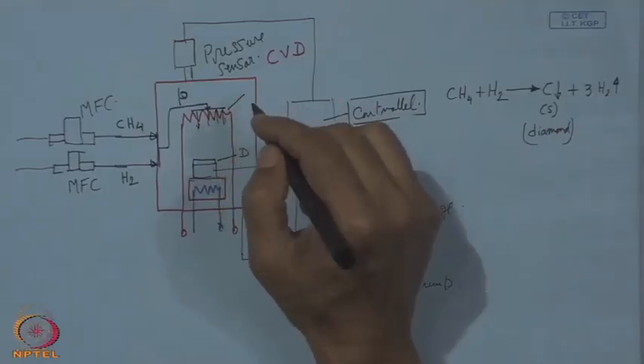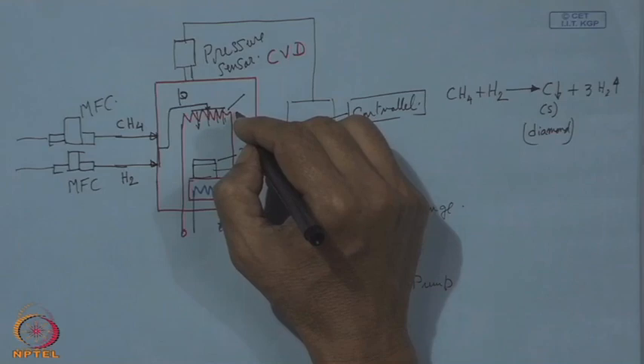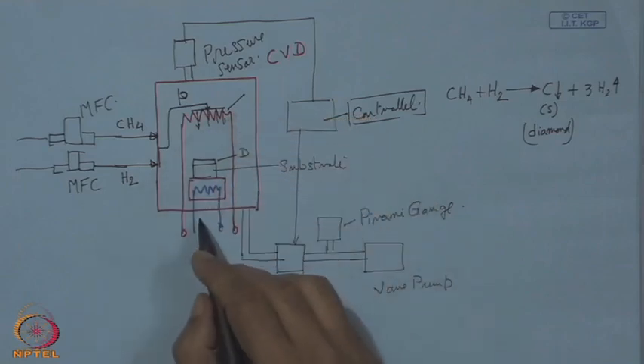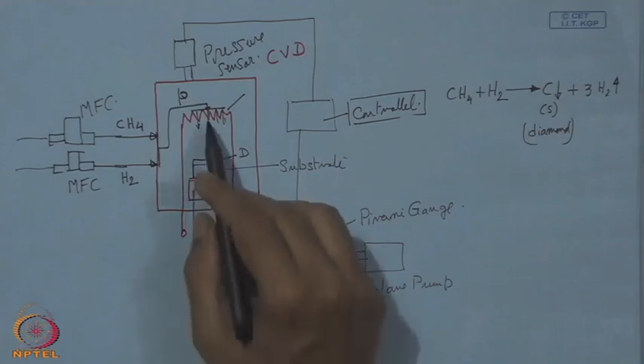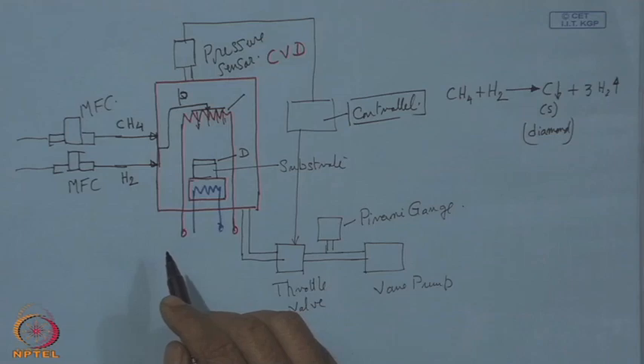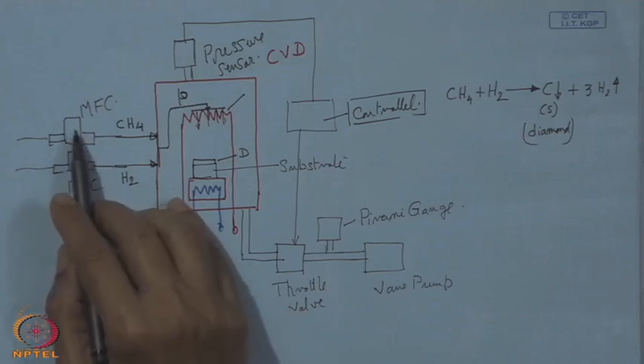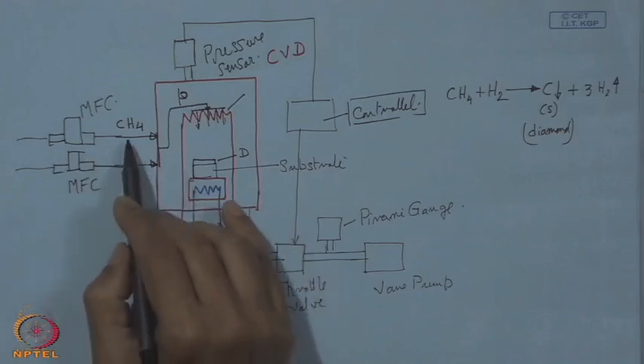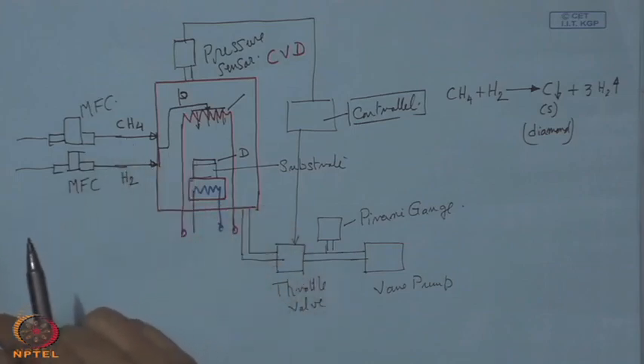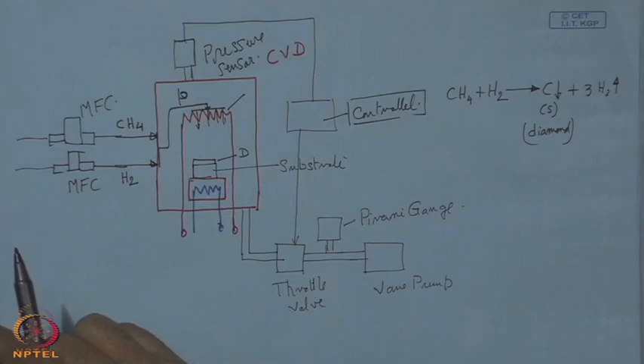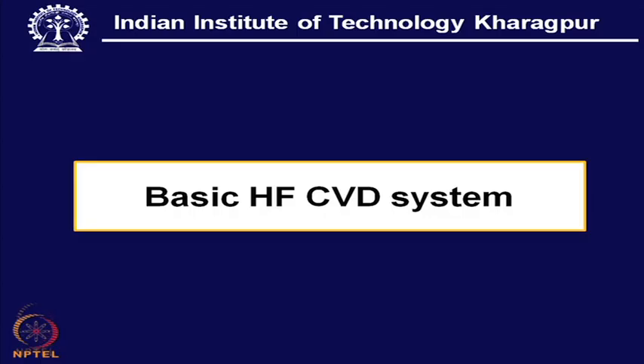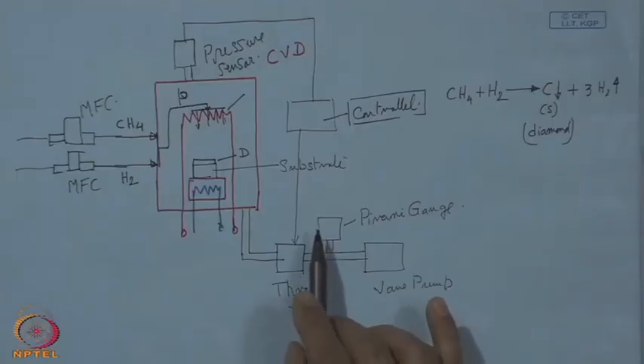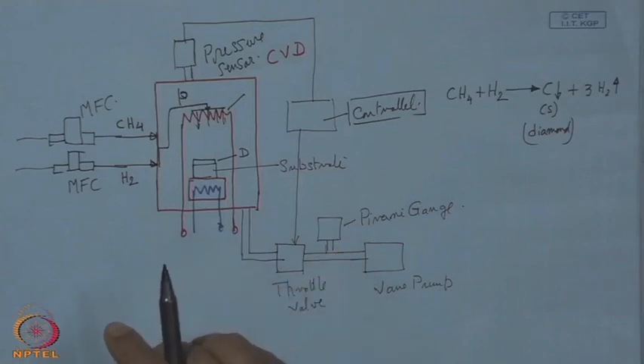Now, here the filament temperature is to be monitored, similarly is the case with the substrate temperature. These are the two requirements. Pressure is obviously one of the parameters, and then the amount of gas flow incoming of CH4 and that of H2, which we shall discuss. So, this is the basic CVD system, we have just discussed what elements we have in the whole process. It is basically a cold wall CVD reactor, because this wall is not heated.